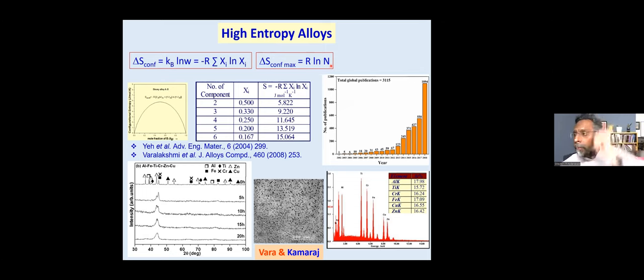As I keep on increasing the number of elements, as you can see in the table below, if I have two components with 50% each, 0.5 mole fraction, this is the configurational entropy, which is 5.8 joules per mole per Kelvin. Whereas if I go to three, maintaining equiatomic nature, 33% each, I see an increase. Go to four component, five component, six component, you see the entropy keeps on increasing as long as you maintain equiatomic nature. And the entropy can be so high that the system prefers not to form any compounds, but to form a simple, what is called a solid solution.